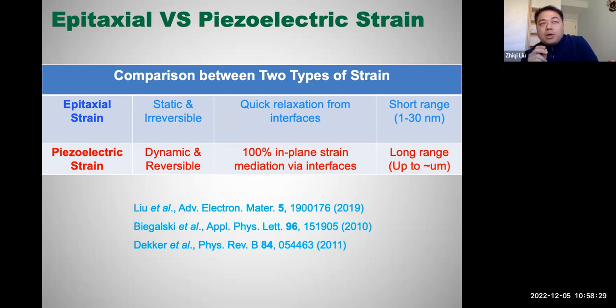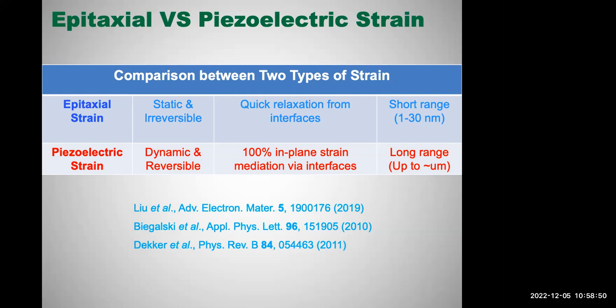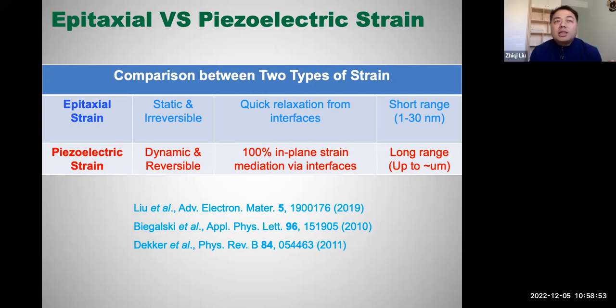Besides, the Berry curvature could also be an interesting origin for the SOT. For example, in the non-collinear antiferromagnets, except for the heavy elements that generate the intrinsic SOC and the spin-Hall effect, you could have the Berry curvature originating from the non-collinear spin structure. This Berry curvature could increase or enhance your SOT efficiency. So it's very difficult to really compare which kind of antiferromagnet would have stronger SOT efficiency.